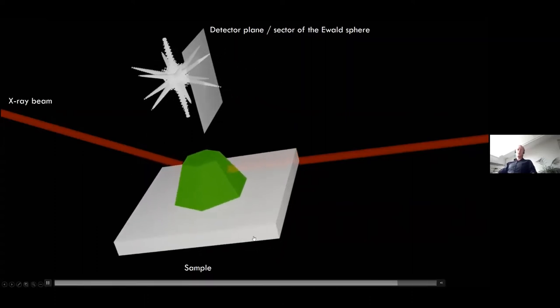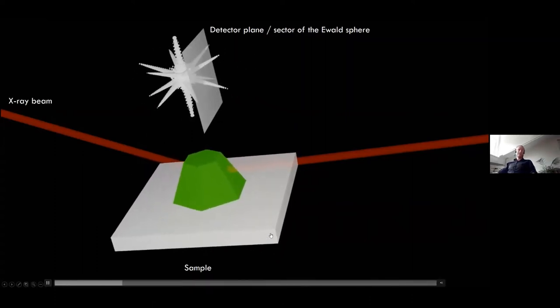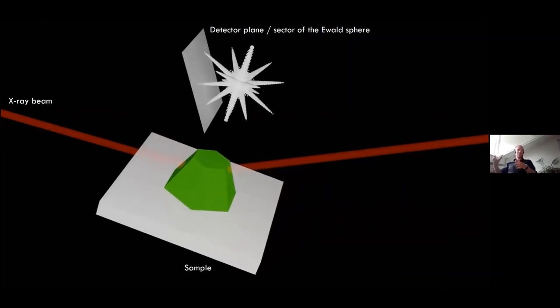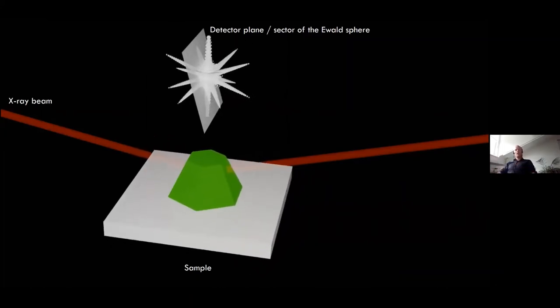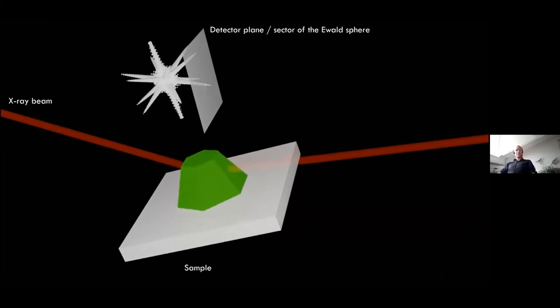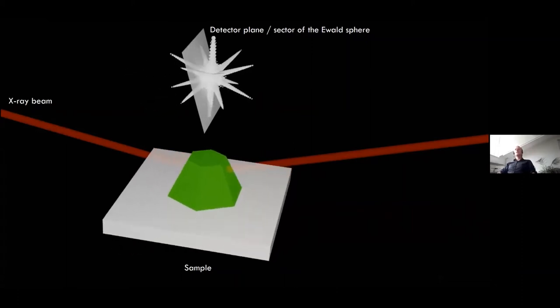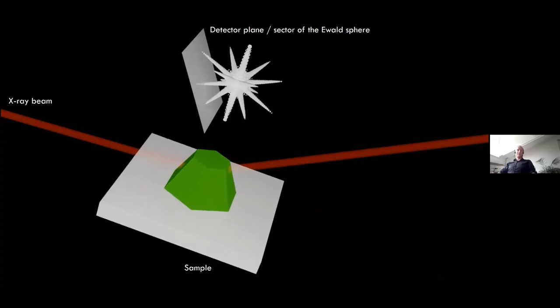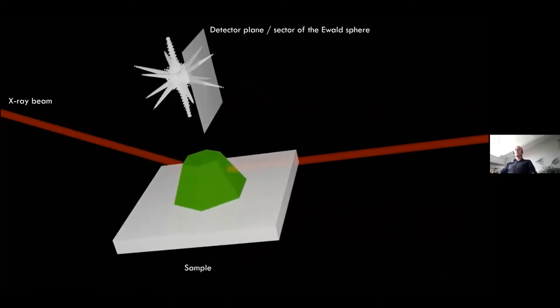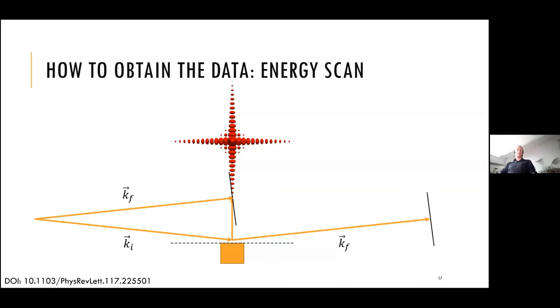Sometimes these movements are making things complicated if you want to use some very stable environment or some special devices on top of your sample and you don't want to move anything. So there is a way to record the same type of data set without actually moving anything on the sample side by changing the energy of the X-rays and keeping the focus on your sample. This way it's called energy scan. So you can start from higher energies or from lower energies.